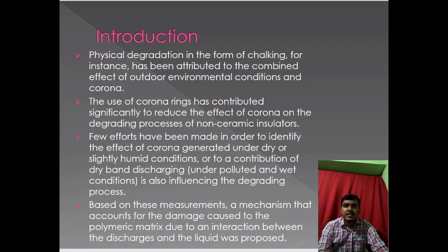This paper deals with the investigation on performance of several polymer outdoor insulators under AC and DC electrical stresses. Here the performance is evaluated in terms of the charge accumulation and decay characteristics as a function of humidity and the tracking and erosion resistance. As we know, the degrading process in polymeric material is mainly due to the corona discharge. Use of corona rings significantly reduces the effect of corona, but not fully.